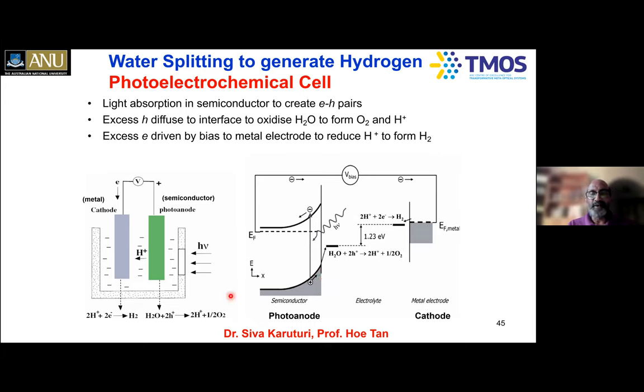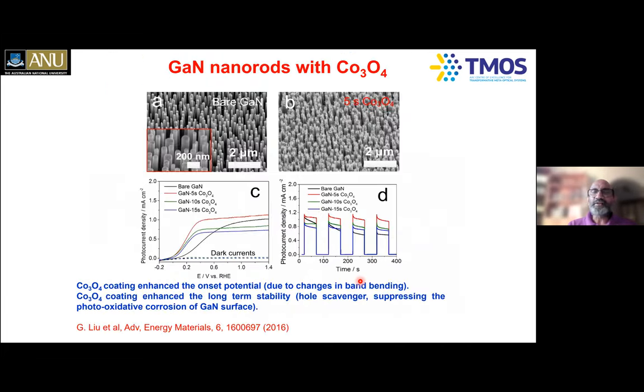Again, this particular work has been led by my colleagues, Dr. Shiva Karuturi and Professor Hoe Tan. The challenge has been that some of these electrodes, anodes or cathodes, are either stable but not efficient, or efficient but not stable. Finding materials which are both efficient and stable has been a challenge for this discipline. So we've taken gallium nitride nanorods, because gallium nitride is typically very difficult to etch chemically, and looked at the photoelectrochemistry, photocurrent density as a function of the potential.